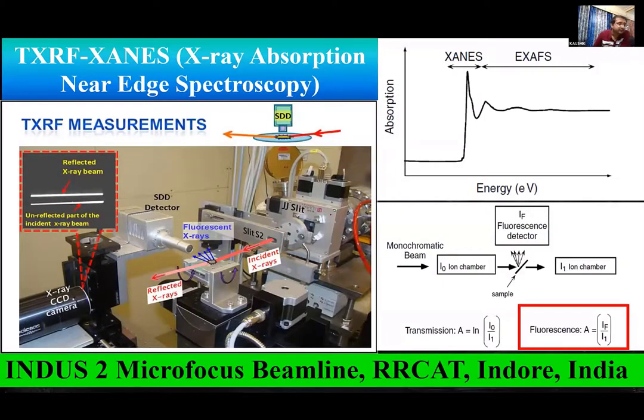All these speciation studies of mixed valent uranium oxide have been done at the Indus-2 Microfocus Beamline at RRCAT, Indore. As you can see, this is the arrangement of the Microfocus beamline, where the beam falls through this slit and finally onto the sample support, at the center of which we have deposited the sample. After that, it gets totally reflected, and at a 90 degree angle there is an SDD detector which detects the signal.